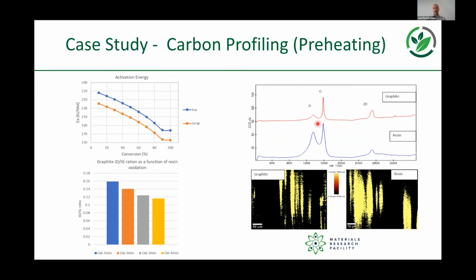And what we can see by analyzing these peaks, without going into too much technical detail, is that the ratio between these two peaks here, the G peak and the D peak, give us an idea of the increased levels of crystallization in the resin and the increased level of ordering that we get and degradation that we get in the graphite. And what we've been able to do is correlate that directly to the oxidation behavior. And that's quite useful for companies, because now what we can do is use a relatively rapid scanning technique to look at how the materials are behaving and degrading.